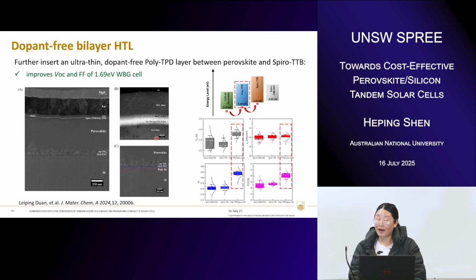And in our real device development, we found that it indeed gave us great performance together with the stability as well as the optical advantages we have claimed just now. At the single junction level, as you can see, this is a cross-section of the cell structure where you can see the layer is really ultra thin, 8 to 10 nanometers, covering the perovskite layer very well. And we were able to demonstrate comparable cell performance using this Spiro-TTB compared to spiro-OMeTAD for the wider band gap. In the meantime, we further improved the cell performance by inserting another dopant-free layer to make a double layer,